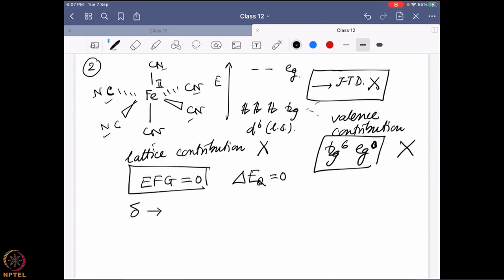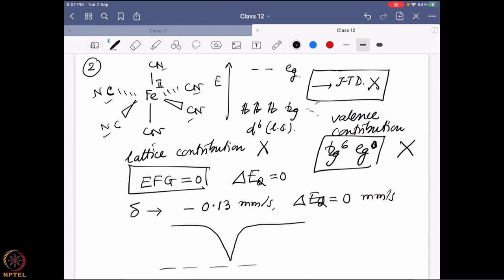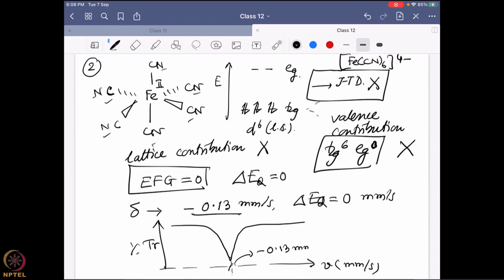The delta value, the isomer shift for this iron system, is minus 0.13 millimeter per second with delta EQ value 0. That means no quadrupolar splitting, and you actually see a single band like this for the Fe(CN)6 system with iron in the plus 2 oxidation state. So you are taking this Fe(CN)6 4 minus system. The charge is 4 minus to show that there is the plus 2 charge on the iron in the middle. And where it is cutting, it is cutting at minus 0.13 millimeter per second.